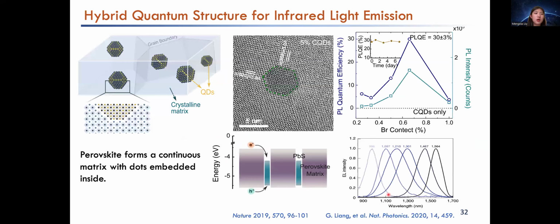And also, if we want to put these quantum dot structures to use for light emission in the infrared, we want to confine all of the electron holes into the quantum dot. So we embed the quantum dot into a high mobility perovskite structure and form a perfect lattice matching between the perovskite and the quantum dot. So when shining light or injecting electron holes into the perovskite, the electron holes can be confined within the quantum dot and finally emit from the quantum dot. This allows us to get a pretty decent quantum efficiency and a very tunable electroluminescence, which is a very successful LED device.